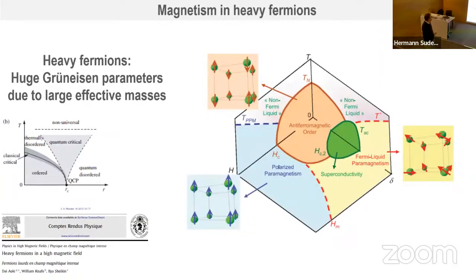And essentially, because of having such high effective masses, you actually maintain a lot of entropy when you go to low temperature. And this means a lot of electronic entropy when you go to low temperature. And this means that the Grüneisen parameter, which tells you the susceptibility of an electron system to changes in the volume, is huge. And because it's huge, these systems are highly tunable.